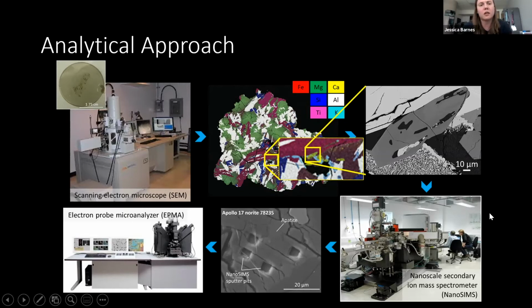The tool of choice that I use to understand the volatile element chemistry is a nanoscale secondary ion mass spectrometer. It's very similar in how it works to other ion microprobes like a 1280, except that NanoSIMS still uses a primary ion beam of cesium, but instead of impinging the sample at an angle, we're using a coaxial system, so the primary beam impinges at 90 degrees to the sample surface. We're sputtering away, literally removing atoms, to look at the secondary ions that come off the sample using a mass spectrometer. For this work, we're mostly looking at relative abundances of chlorine 35 and 37.